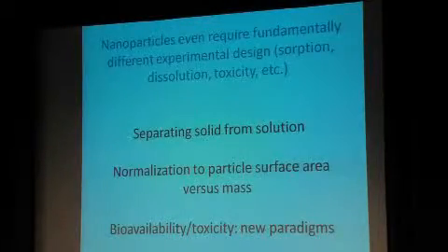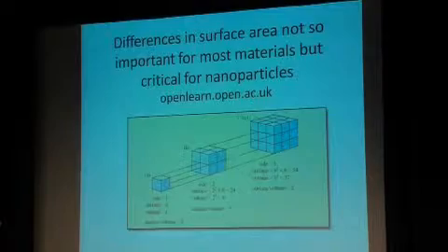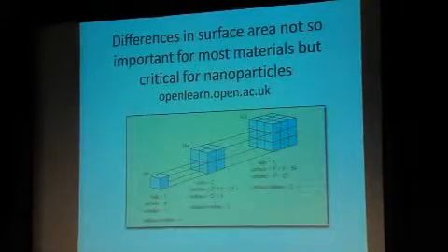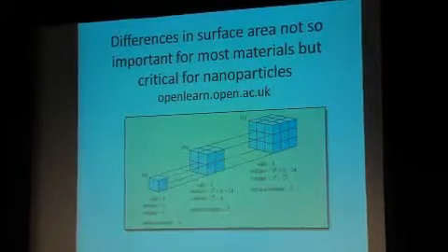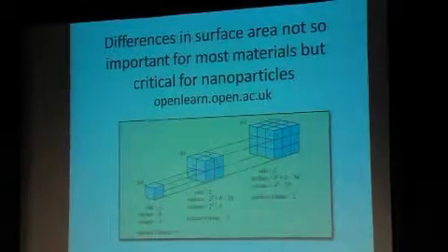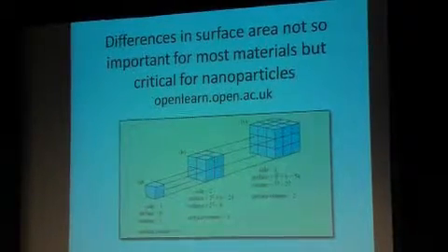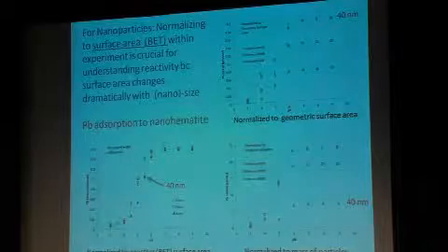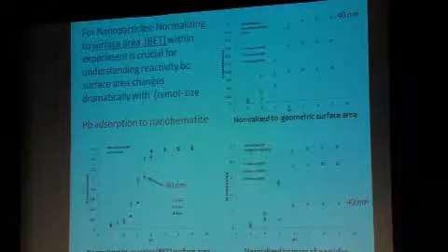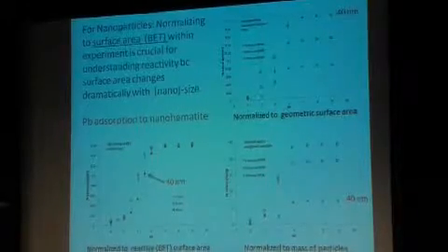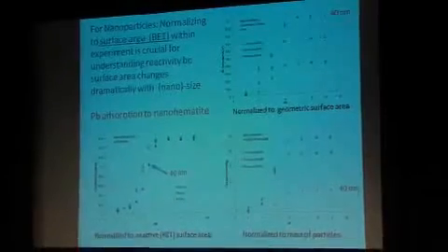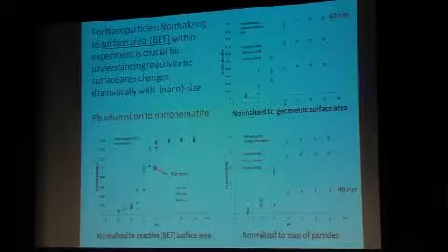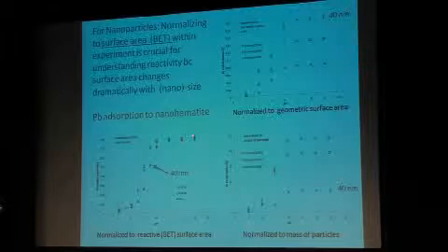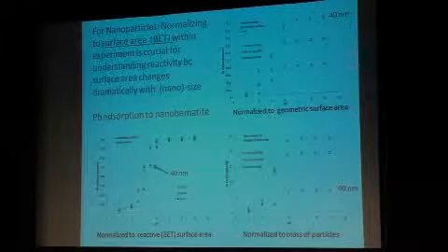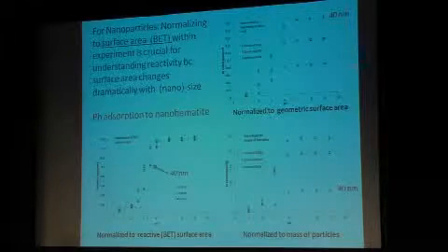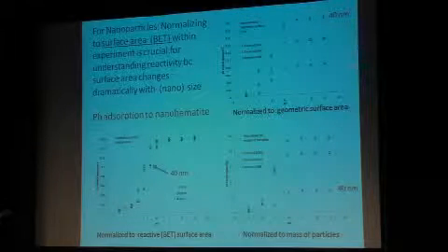So let's go on to one last thing I wanted to talk about, one last point. This issue of surface area. We've mentioned it so many times, but it's not usually considered correctly in experiment after experiment. Here is an example where my student ran an experiment of lead adsorbed to hematite at different particle sizes. I already showed you this data. And it shows that the 40 nanometer particles adsorb a little bit differently from the 3.6 and 8.6 nanometer particles. So size has an effect.